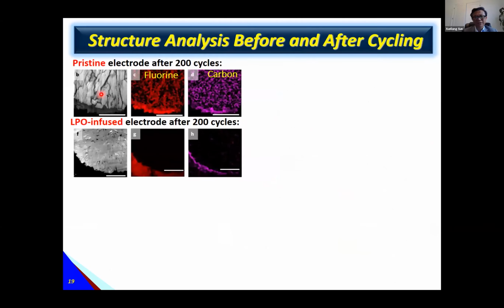For example, without coating after cycling, you can see some cracks, and we also found signals of fluorine and carbon, indicating the liquid-based electrolyte penetrated inside the particle. But if you use the coating and annealing, we cannot find the cracks, and also no signal of fluorine and carbon, indicating the coating layer on the grain boundaries blocked the reactions.